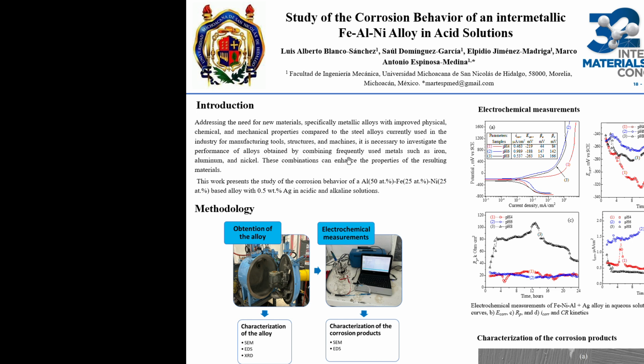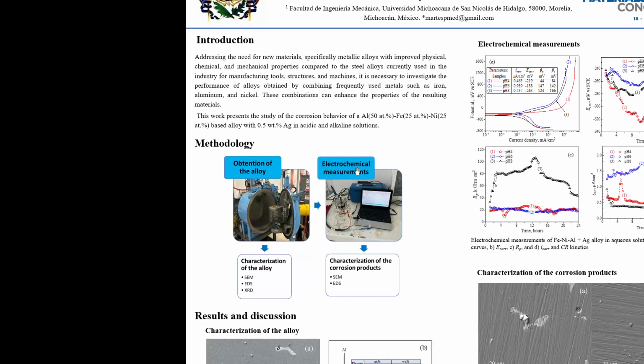Methodology. In this way, the corrosion study of cast aluminum, iron, nickel-based alloys in acidic and alkaline solution was carried out using electrochemical techniques. The alloy was obtained by melting pure metals in a vacuum induction furnace. In the first step, the iron and nickel were melted, and then the aluminum was added. This base alloy was recast to add high purity silver content and cast into a metallic mold. Samples with dimensions of 1 by 1 by 0.5 centimeters of alloy were cut by wire electro-erosion, polished with sandpaper, and cleaned in an ultrasonic bath with methanol.